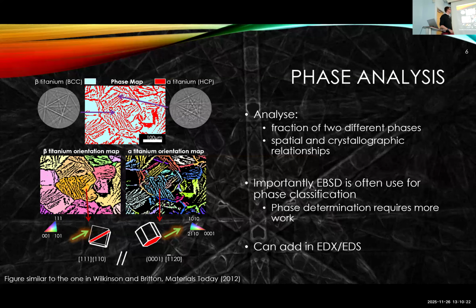We can use this to look at, this is from my own work, aerospace grade materials. Here we're looking at a titanium and molybdenum alloy. This is a really nice example to show you that we can map the balance of different crystal phases. We have a molybdenum-rich body-centered cubic phase. We have a hexagonal titanium-rich phase. And we can see the diffraction patterns at each point are different, but the computer has solved this for us to tell us about the phases.